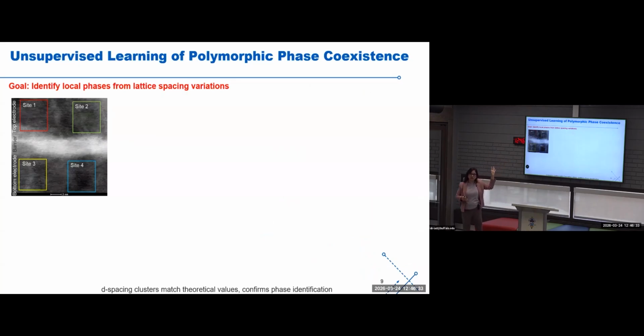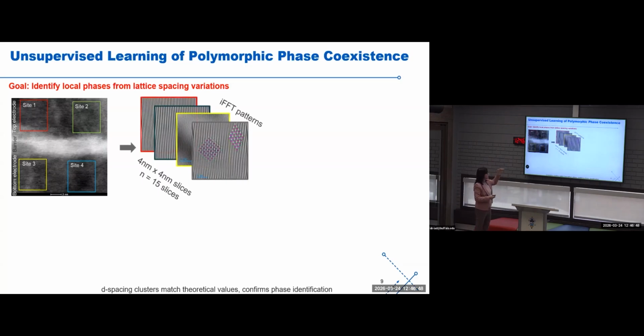But this doesn't say much, because in TEM there are sample preparation issues, there are thickness issues, there are artifacts, because microscopy has artifacts, most of the microscopy. So we can have that. So, not getting biased by just the imaging, we wanted to check the inverse fast Fourier transform patterns.